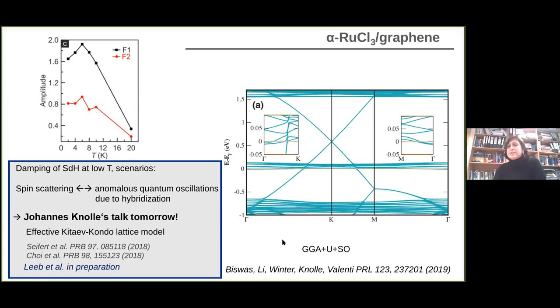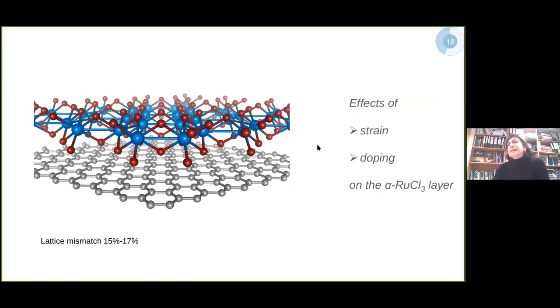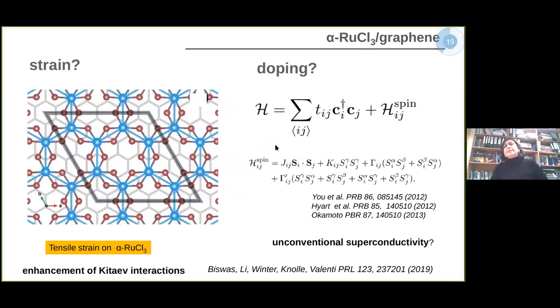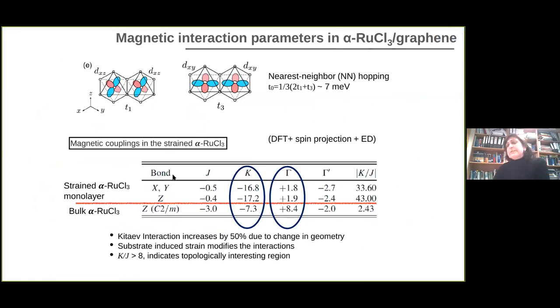And I want now to go to this question that I was asked about the strain. So let me now concentrate on ruthenium trichloride, what happens to it in terms of strain and doping, which we just commented on a little bit. As I was showing, this comes from our simulations, and what we saw is that there is an important tensile strain. And let me show you in the next slide what it produces. Because it's tensile, the rutheniums go apart from each other, so I'm getting rid of this detrimental hybridization, which is in fact responsible for the gamma interaction.